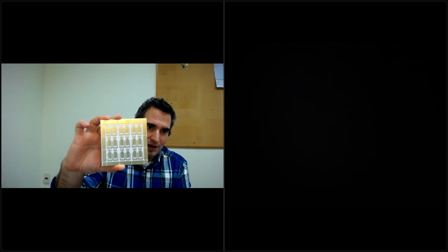What we then do is, depending on your requirements for plating, in some cases, our customers just want raw copper. But more often than not, our customers want a plated structure. So what we'll do is we'll electroless plate nickel and gold if you'd like. We can do a flash of gold. We can do upwards of over 100 microinches if you wanted. Why anybody needs that much gold, I don't know, but we can give it to you. And you can see here, here's a DBC structure that has gone through all the processing that we've gone through and has been plated, nickel and gold.